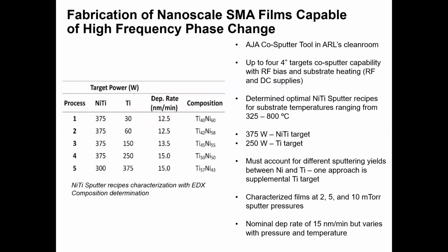So all of the depositions were carried out in the ARL clean room using an AJA co-sputter tool. 4-inch targets of equiatomic NiTi and titanium were used to determine the sputtering parameters, which would yield equiatomic or slightly titanium-rich compositions. The equiatomic recipe turned out to require 375 watts of DC current applied to the NiTi target, and a simultaneous 250 watts of DC applied to the titanium target.